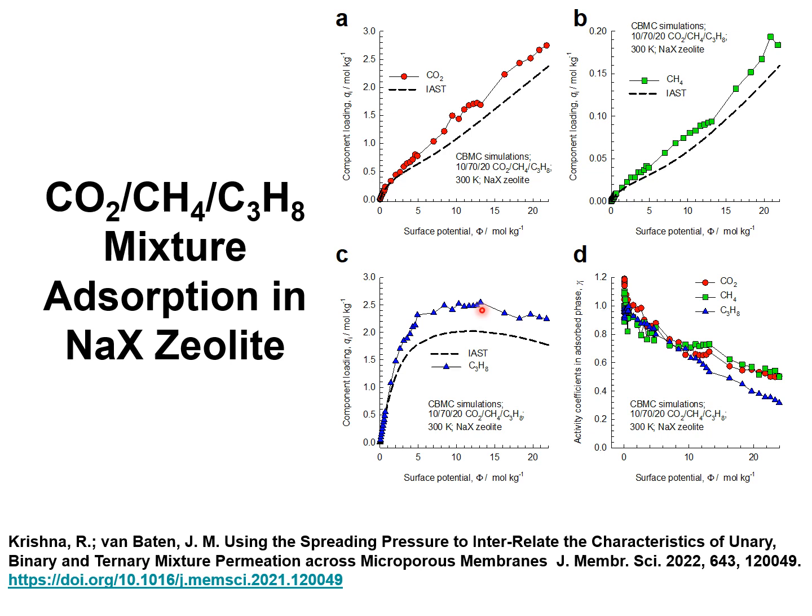because thermodynamic non-idealities influence the loadings of all three guest molecules. The activity coefficients determined from CBMC simulations here are plotted against the surface potential.